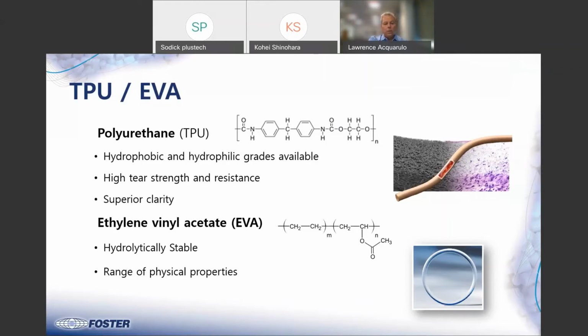But one of the outstanding features of an EVA is that you can control or change the vinyl acetate content, and that will allow different drug delivery rates. So you can get very, very good controlled delivery rates out of an ethylene vinyl acetate, and it's been a very successful material for drug delivery.